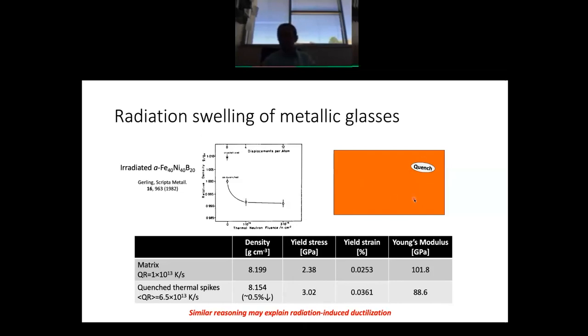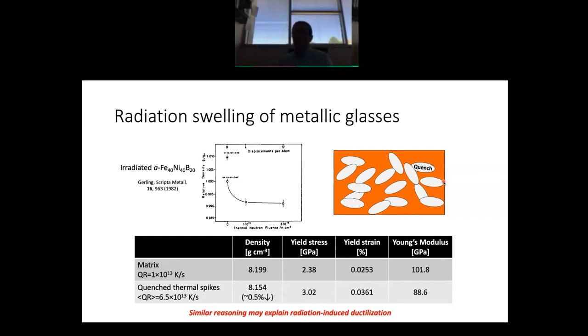Well, based on what I've shown you, we can explain this as basically the quenching of a thermal spike, as I'm showing here, generating a low density region, then more and more thermal spikes that eventually start to overlap. And once they've actually covered the entire material, once the entire volume of the material has been exposed, the entire density of that glass has changed. Okay, this also causes changes in the yield stress of the material, as well as changes in the propensity for shear localization. I'm not going to talk about that here, but basically similar reasoning to the one that we use here for density can be used to explain ductilization of metallic glasses thanks to radiation.